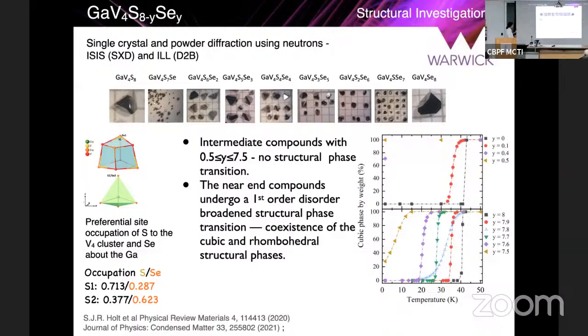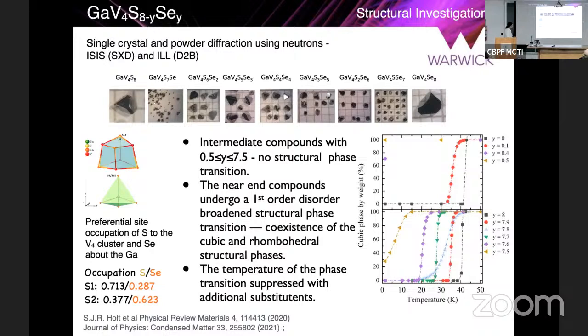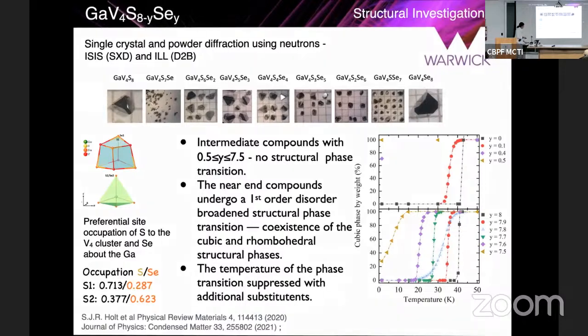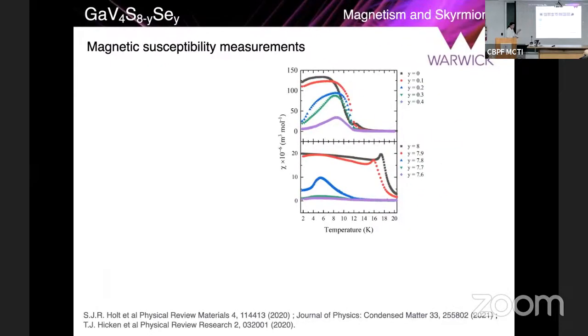So when we look at the structural transition at compositions very close to the end compounds, which I've plotted here in very, very minute steps, very carefully synthesized powder materials, we find that the structural transition exists only for phases very close to the two end phases, but not for any of the intermediate phases. You see a very broadened sort of transition, and the temperature of the phase transition is strongly suppressed as you add more substituents in it. Another way of characterizing these is also to study the magnetic properties.